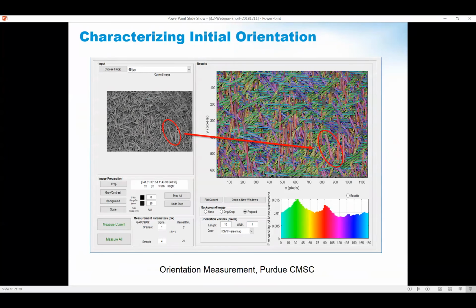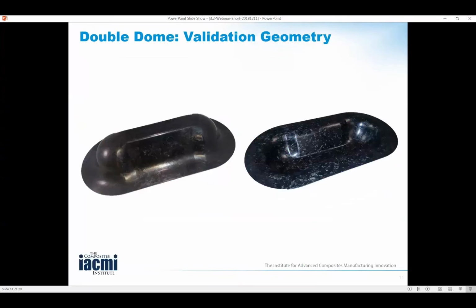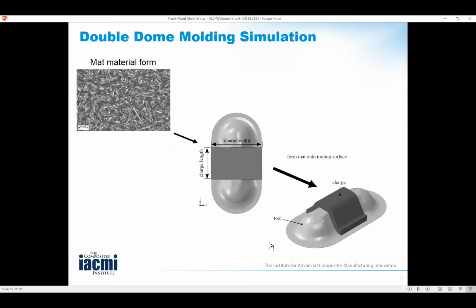platelet charge, this charge consisting of these platelets, take this orientation, and now simulate the manufacture of a real part and understand where those platelets flowed and realigned during that manufacture. And here we're going to look at this double dome part initially, and then I'll bring you back to a lift gate at the end. But we're going to do a lot of training on this double dome to understand the effects of flow. So we start with that mat of the pre-preg platelet molding compound. We drape it over a mold, and then bring two-sided tooling together and flow the mat to form a part.